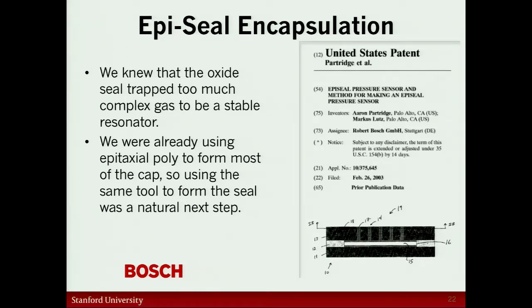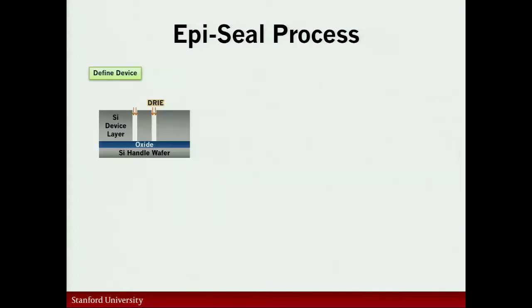We didn't want to invent something that was cool and useless. So the goal was to try to develop something that actually, if we got something right and it was interesting, there are people who would know how to make more of it, and we could go down a faster channel. So among the things you could deposit, we thought about depositing metals, we thought about depositing other materials, ultra-high vacuum techniques. We already had this Epi-Poly process that we were using to grow the first half of the cap, so it was kind of obvious to try that as well. We could just seal up the part by growing more Epi-Poly. And so let me just take you through how this sequence works as an example.